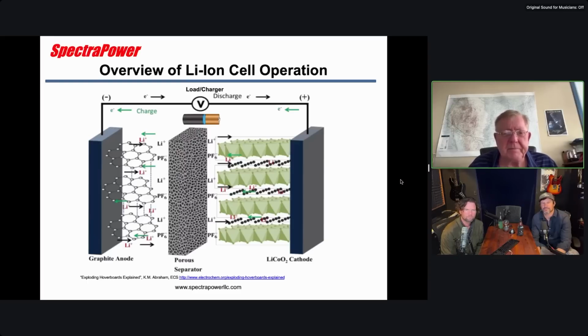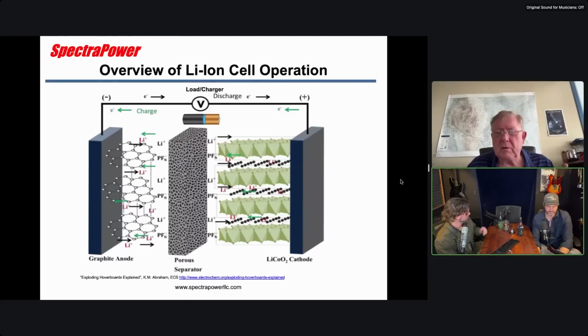What they do is they take this porous separator, which is just a thin white plastic sheet, very thin. They make that a solid sheet, so it's a solid sheet of plastic or ceramic, and then they put that between the electrodes where the separator would normally go. One of the problems they have is they're trying to get rid of the liquid in the cell, because remember I said that's very flammable, right? Yeah, the electrolyte.